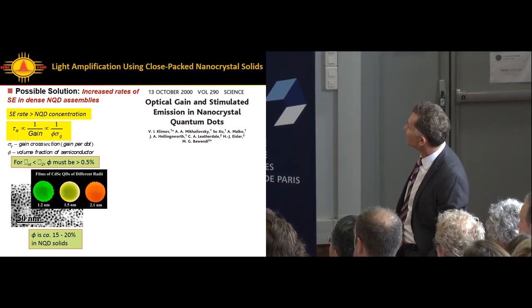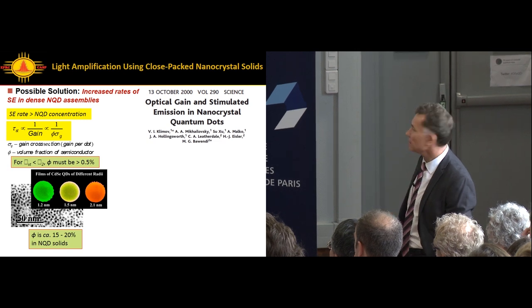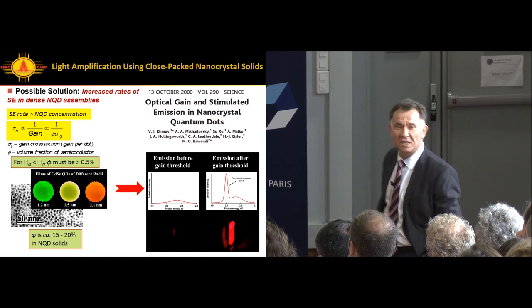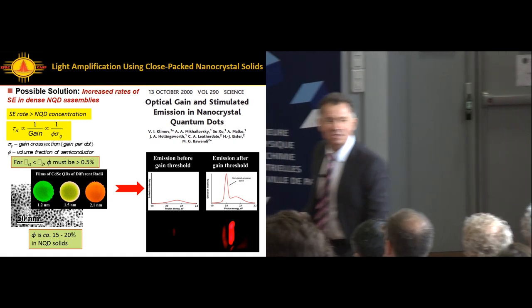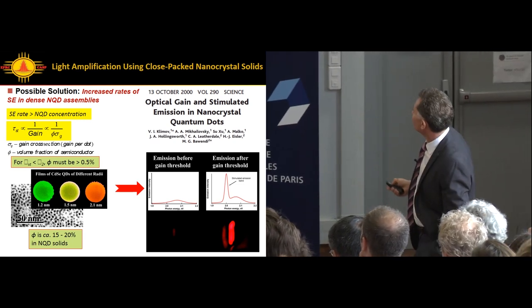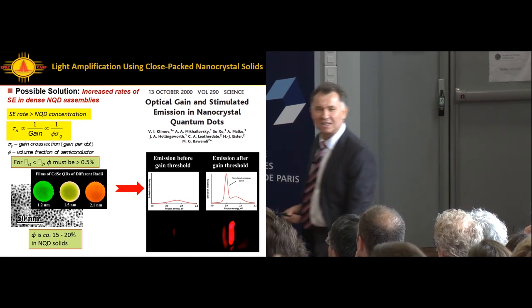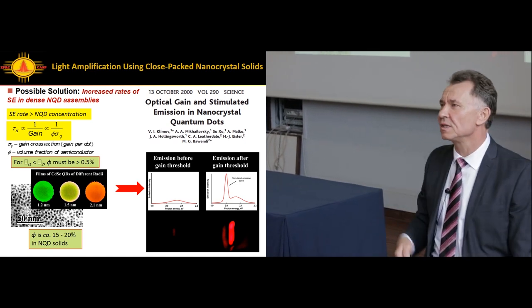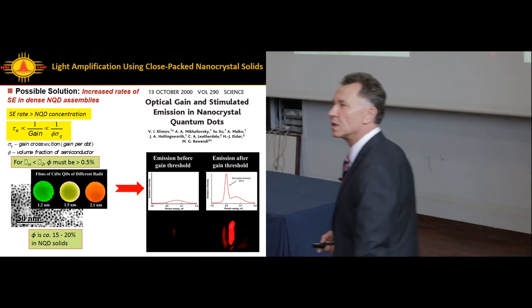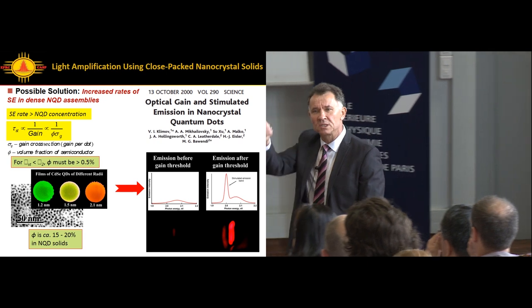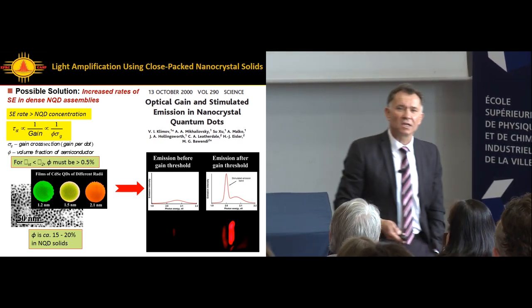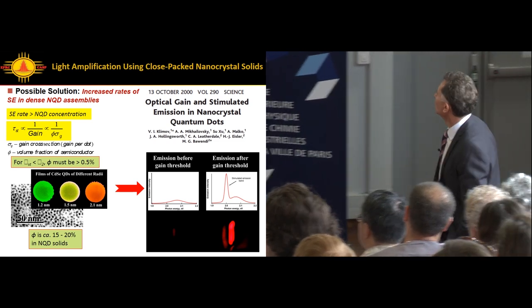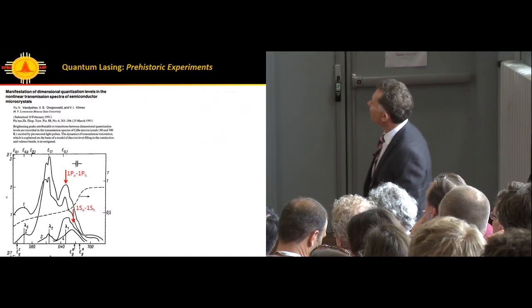Using Moungi's quantum dots, we assembled them into these types of solids. This is what we got. Quite exciting. Sasha Mikhailovsky was the first to observe this in the lab. This very nice amplified spontaneous emission feature, single-pass lasing essentially. Eventually we did more work putting our quantum dots in different types of cavity, DFB cavity developed by MIT, ring cavity which we utilized at Los Alamos.